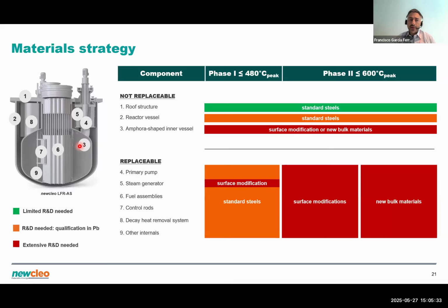And lastly, red color code is where we need extensive R&D. And this applies in general for all components when we move to a higher temperature phase. But already in phase 1, this applies to some components, and specifically to this amphora-shaped inner vessel, component number 3 here, because it will be installed from day 1, but it will move from phase 1 to phase 2 without being replaceable. So that means this component already requires some sort of surface modification or the use of a new material already in phase 1. And a similar thing could happen to the steam generator tubes, because these tubes contain heated steam on the inside, or boiling water, and hot lead on the outside.